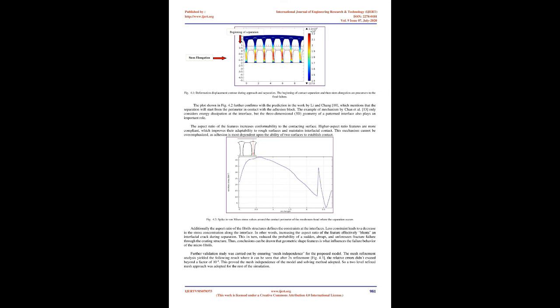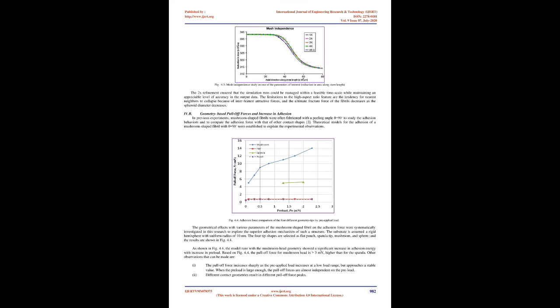For van der Waals interaction, the separation energy usually ranges between 10 and 50 mJ/m2, which is assumed as 10 mJ/m2 according to theory 21. The effective equilibrium distance of van der Waals force is taken to be E equals 0.23 nm. We also adopted RTH equals 20 MPa according to earlier research by Johnson et al. 17. At each equilibrium step, the local interfacial stress is shown to be dependent on the varying clearance and deformation according to Equations 1 and 2.